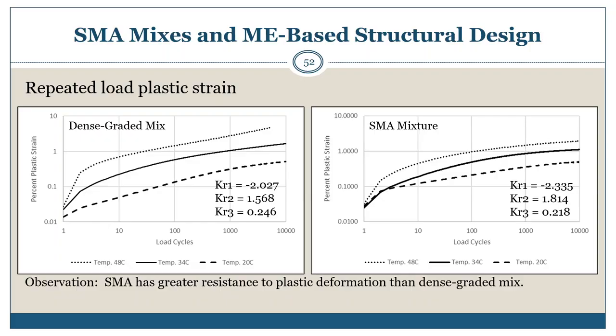The lower KR3 value, or slope, the more resistant the mix is to long-term rut depths. In other words, lower rut depths exhibit higher levels of traffic over time. So in comparison of these two graphs, the KR1 value has a significantly higher negative value for SMA mixes and a lower KR3, or long-term rut depth value. The KR2 value is higher for SMA mixes, meaning more temperature susceptibility, but overall the SMA mixes would result in lower predicted rutting for these laboratory measured values in comparison to the dense graded mixture.